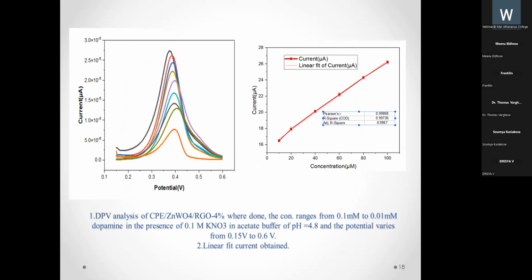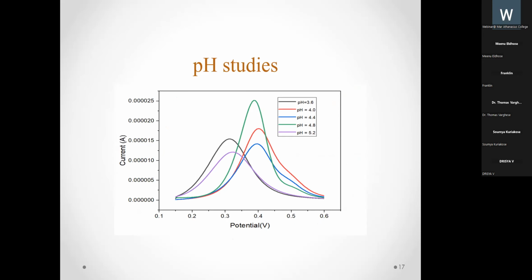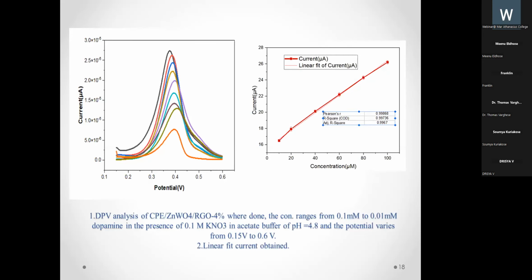And this is a DPV analysis of CP zinc tungstate RGO 4%, because I have done the DPV analysis of 4% alone, because in the graph of CV, the 4% shows the maximum peak height. So the DPV analysis was done using this particular CP zinc tungstate RGO 4% composite only.